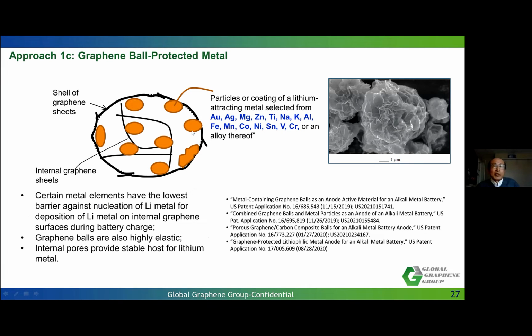And also because of the presence of those transition metal elements, it serves as a preferred site for lithium metal deposition. And we allow the lithium metal to get deposited onto the surface of graphene here inside the structure in such a way that there will be no dendrite. And then the internal pore, again, will provide the stable host for the lithium metal here.